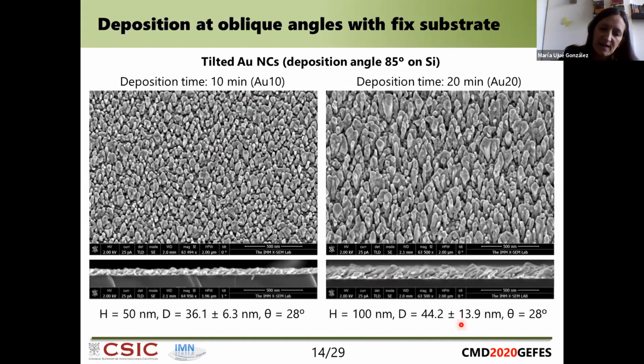Here you see they are 44 nanometers, and also the dispersion is bigger. But the tilt is the same in the two cases. That doesn't change. And so we try to see which were the optical properties and if these kind of coatings were interesting for SERS.